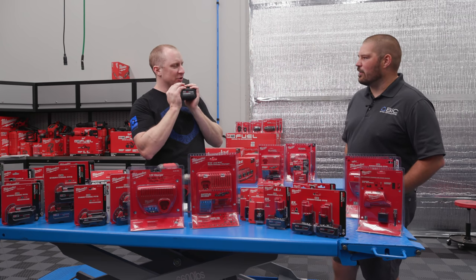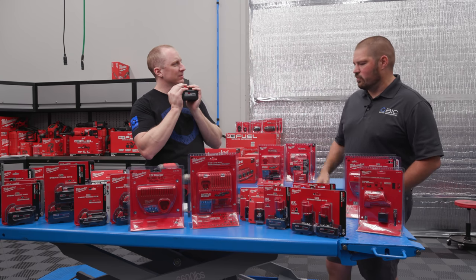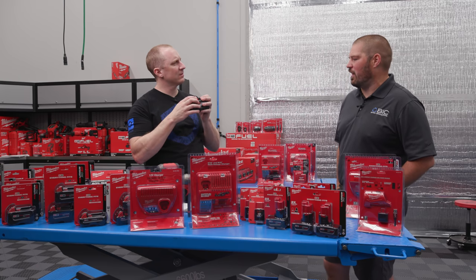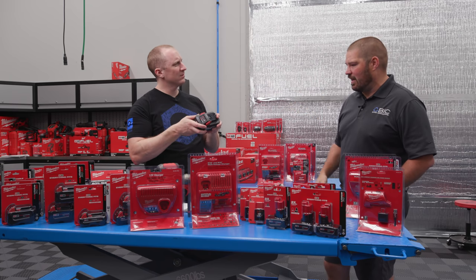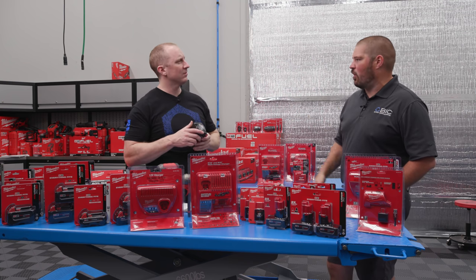Yes — they do that for the cycles they tell you about. But the best thing users can do is keep batteries at a lower charge. I have original 5.0 and 3.0 batteries that are 4.5 years old, and I've aged about 1–2% capacity. Friends who charge theirs every night to 100% have lost 10–14% capacity. It's orders of magnitude more capacity retained by avoiding constant top-off charging.